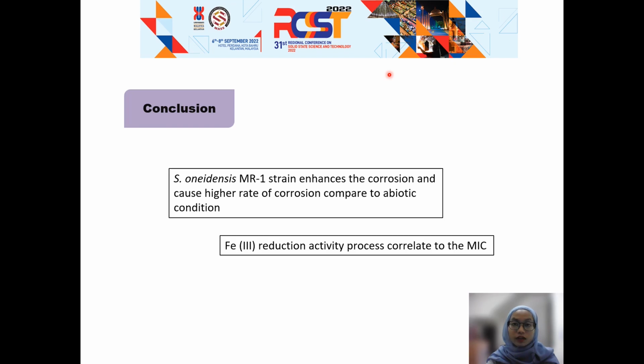The cracks on the surface also provide evidence that pitting corrosion had occurred. Reduction of iron 3 was correlated to the corrosion process with the increasing of iron 2 concentration. Therefore, the activity of Shewanella oneidensis MR-1 and microbiologically influenced corrosion are correlated to each other.